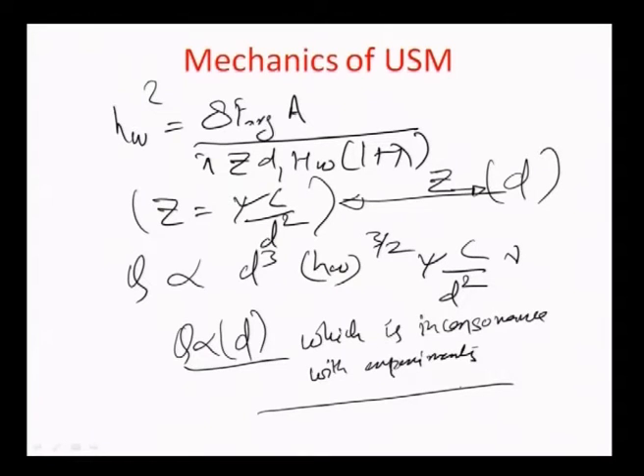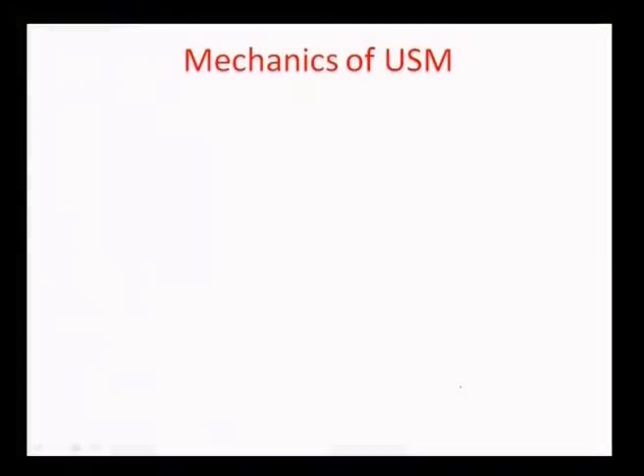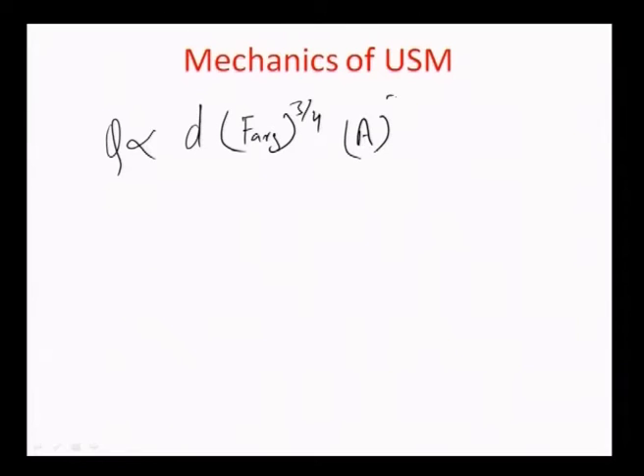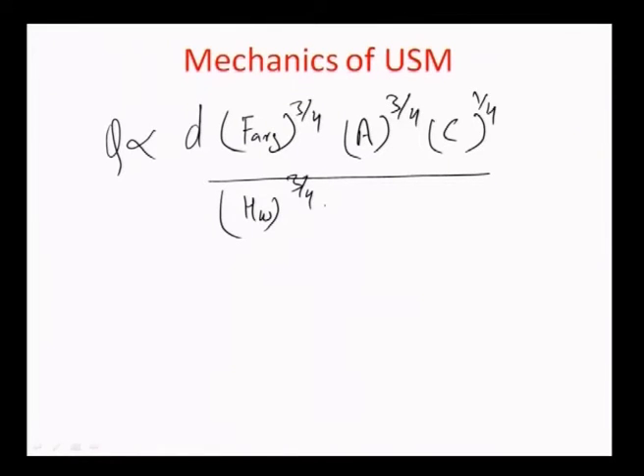So what I will try to do now is evaluate some of the typical characteristics of how Q will vary with what parameter. So let us write this whole thing down here. Q, as you know now, is proportional to d times the average force F average to the power of 3 by 4 times the amplitude of motion of the tool to the power of 3 by 4 times the concentration C to the power of 1 by 4, divided by the hardness to the power of 3 by 4, (1 plus lambda) to the power of 3 by 4, times nu, where nu is the average frequency.